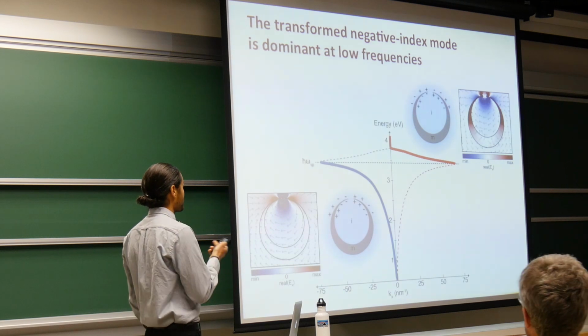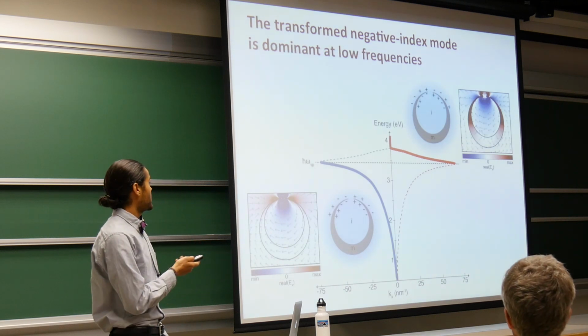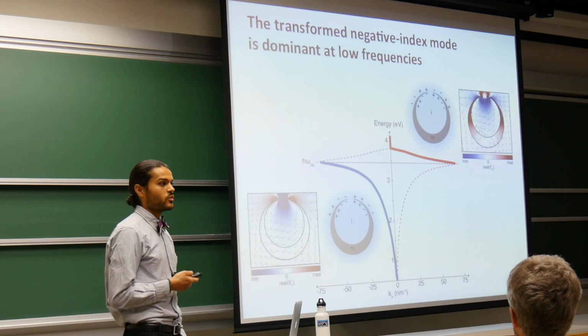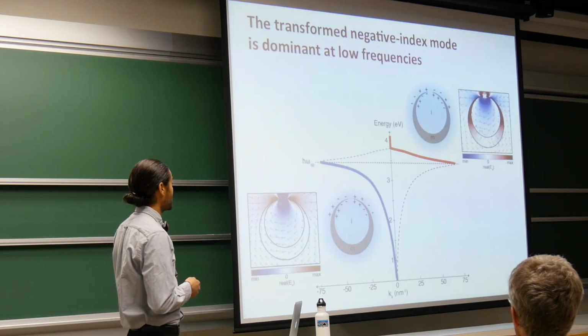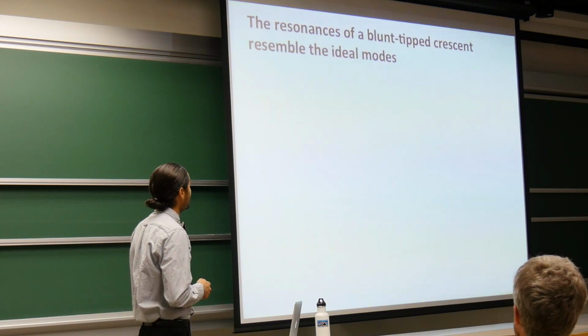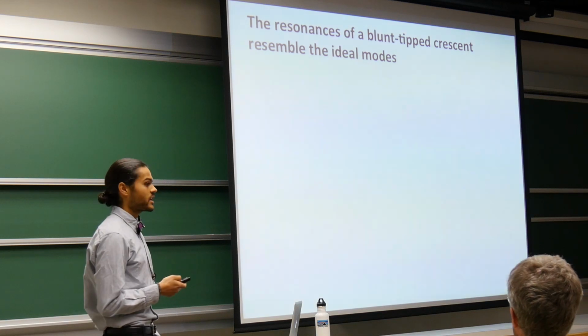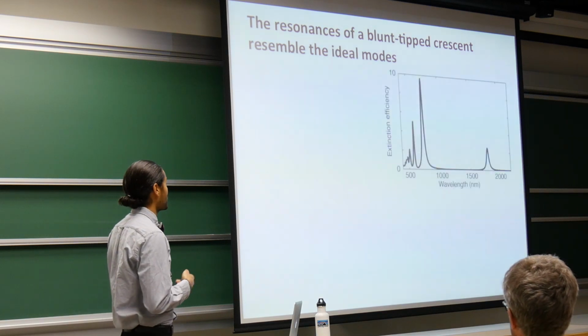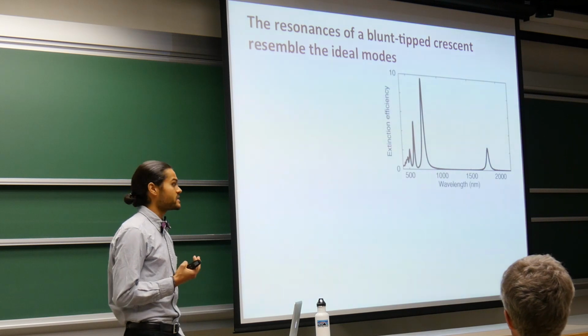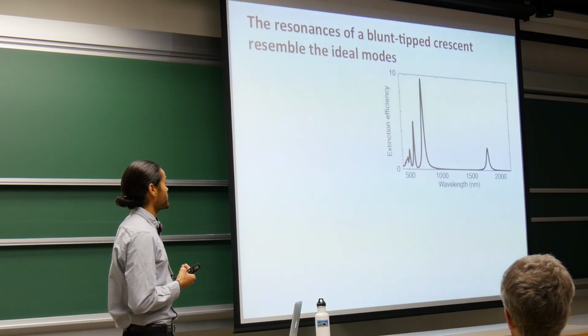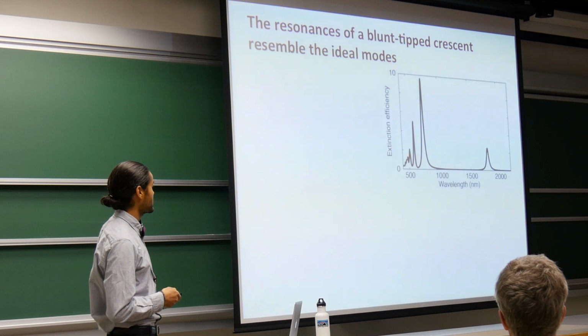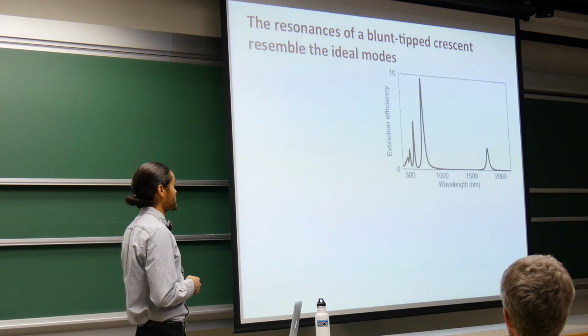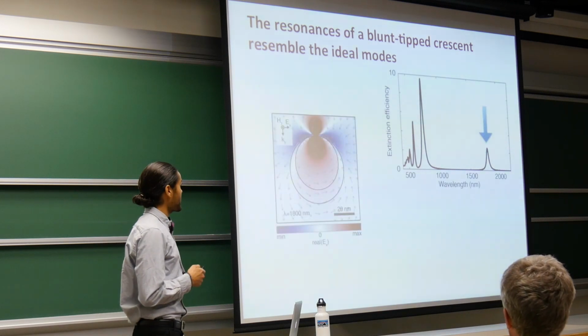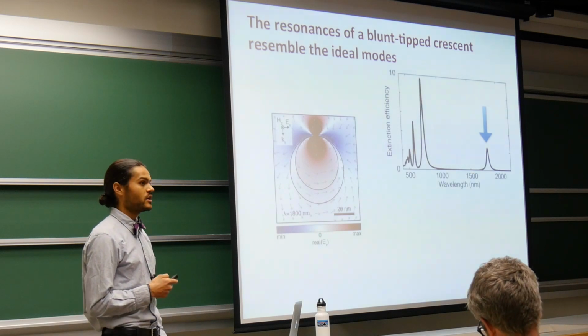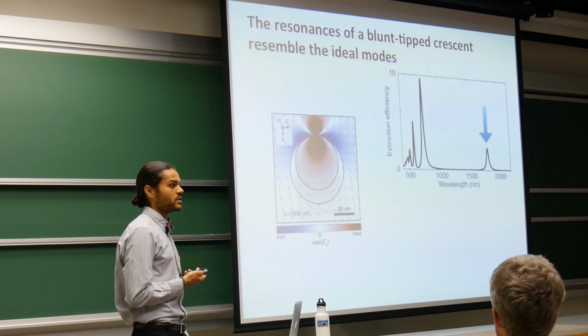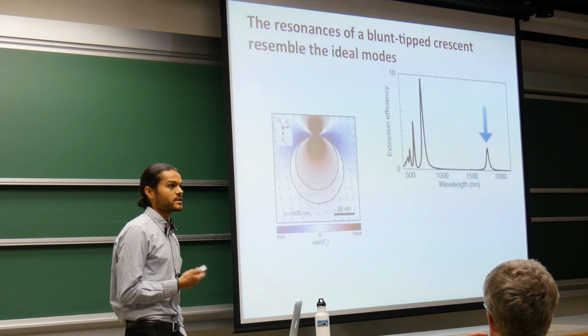And so what we'd like to do is find out whether the same sort of mode characteristics are preserved when we round the tips of the crescent and consider a more practical structure. So as we expect for a finite resonator, we do see resonances appear in a spectrum. In this case, we've calculated the extinction efficiency of the crescent resonator using a finite difference time domain. But if we look at the lowest energy resonance of the structure, we see that it essentially looks identical to the mode that we were exciting in the singular structure.